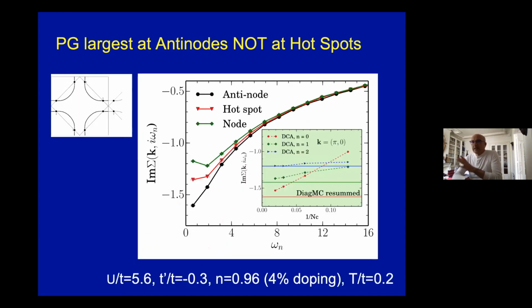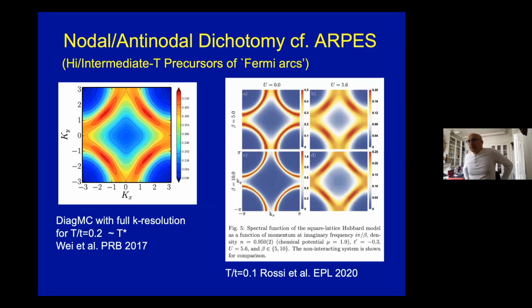And I want to emphasize that here we are in a regime of pseudogap formation which is very different from the weak coupling pseudogap we had before. The correlation length is actually not large. And the formation of the pseudogap is largest at the antinode rather than at the hotspot. So in that strong coupling regime, the notion of hotspot, at least in that temperature regime, is not a relevant notion. Okay, correspondingly with the pseudogap formation, if you compute something like a contour map of the spectral function, there is, of course, the formation of apparent Fermi arcs, with more intense quasiparticles near the nodes and less intense in the pseudogap near the antinodes.